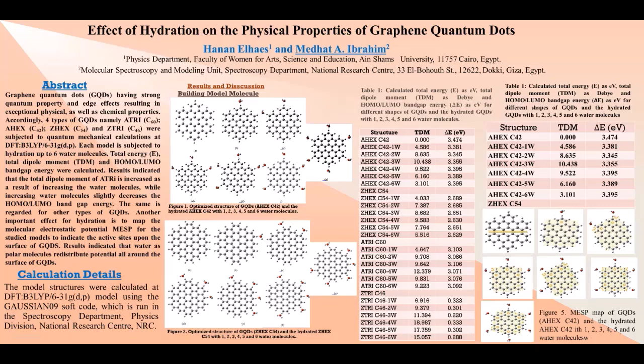were subjected to quantum mechanical calculations at DFT B3LYP 6-31G d,p. Each model is subjected to hydration up to 6 water molecules. Total energy, total dipole moment, and the highest occupied molecular orbital and lowest unoccupied molecular orbital bandgap energy were calculated. Results indicated that the total dipole moment of the armchair triangle is increased because of increasing the water molecules, while increasing water molecules slightly decreases the bandgap energy.